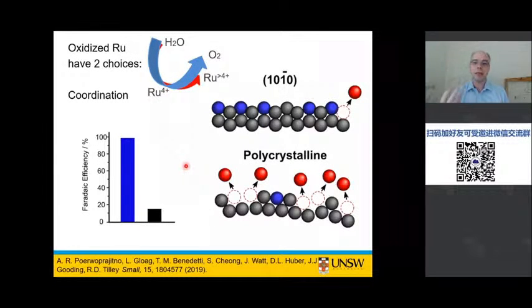So if we want to think a little bit more, and this is some of Agus's work that was published in Small, about how we can make these stable, active catalysts with these low index facets with ruthenium, then essentially we need to think about what the ruthenium is doing during OER. When we oxidize the ruthenium to these higher oxidation states on the surface of our catalyst, these oxidized ruthenium atoms have two choices. They can either stay on the surface and catalyze your OER process, or they can dissolve up into the solution.